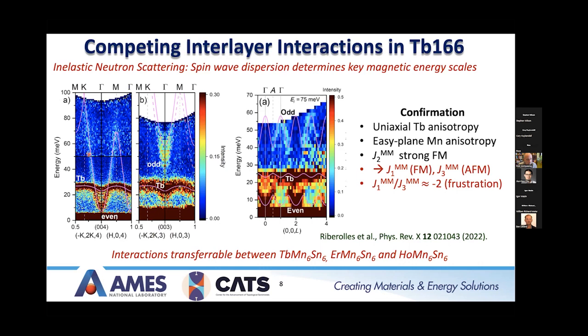And these pink lines here correspond to fits to that Hamiltonian we built up prior. And then in the mid-range here, these manganese modes extend up to high energy. In the mid-range here, just below 30 meV, you have this terbium mode, which is slightly dispersive across the zone.